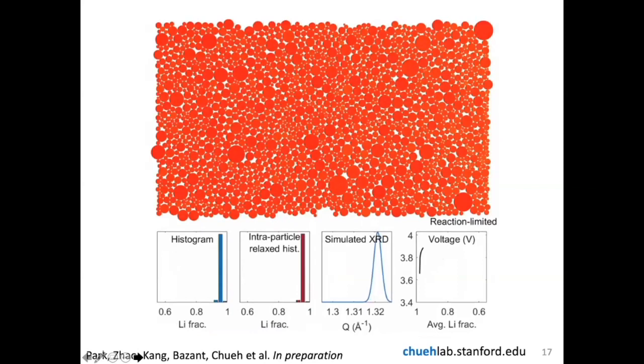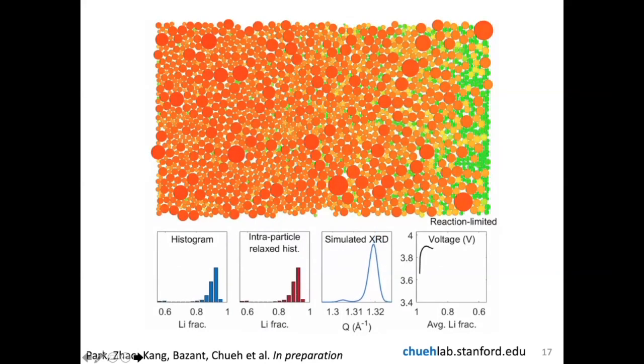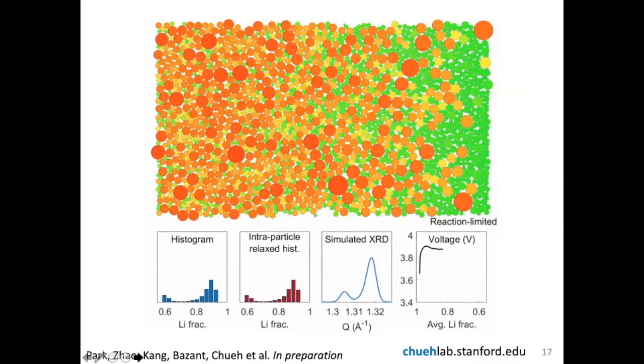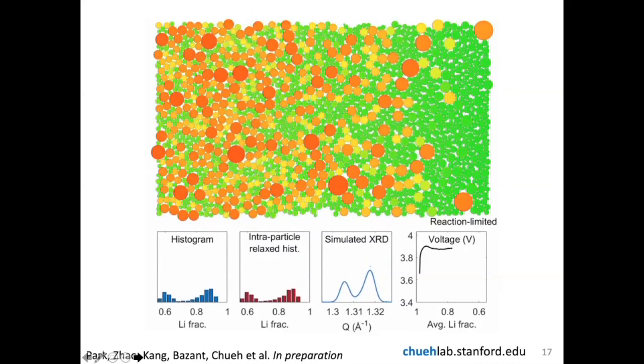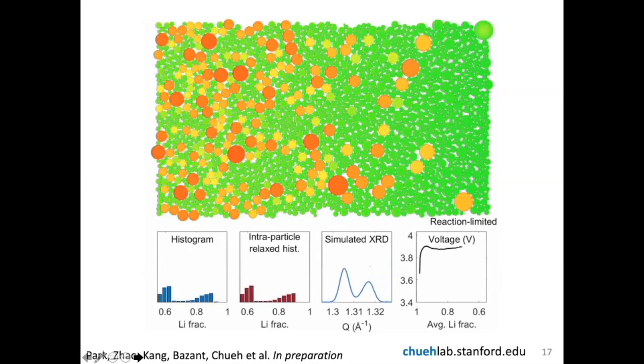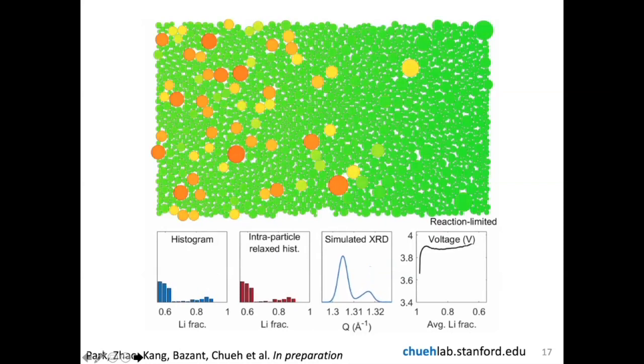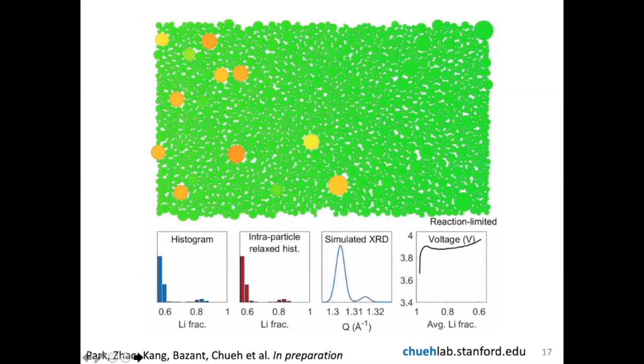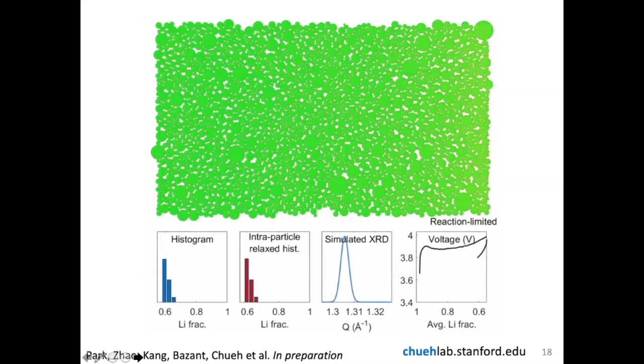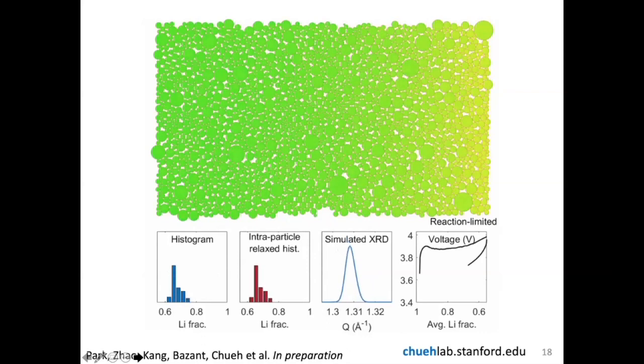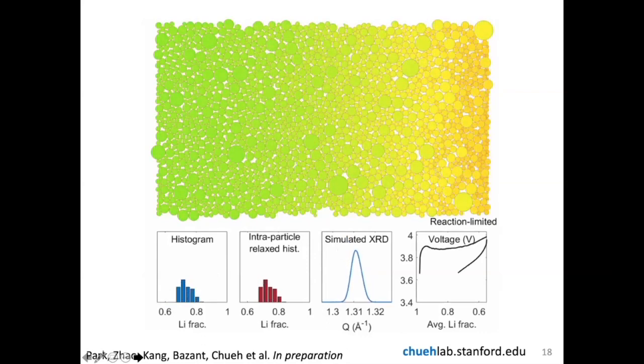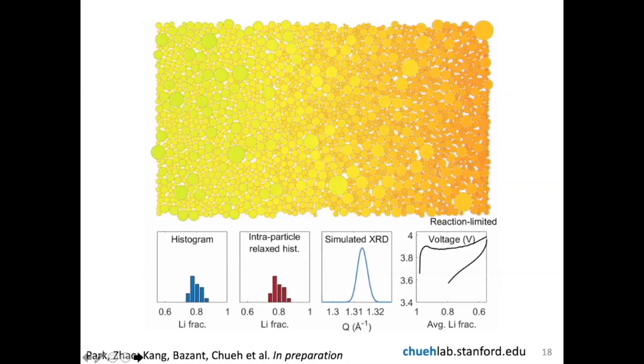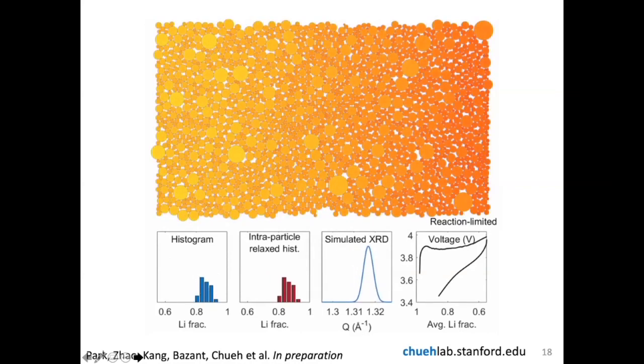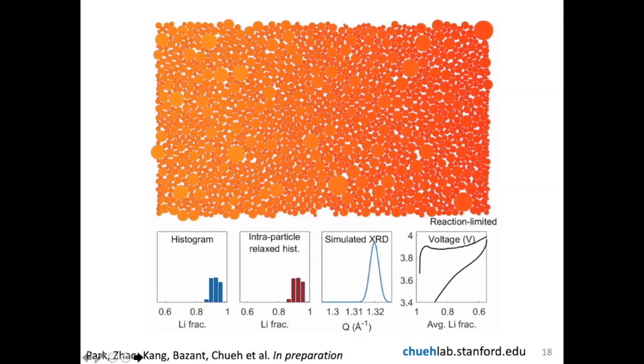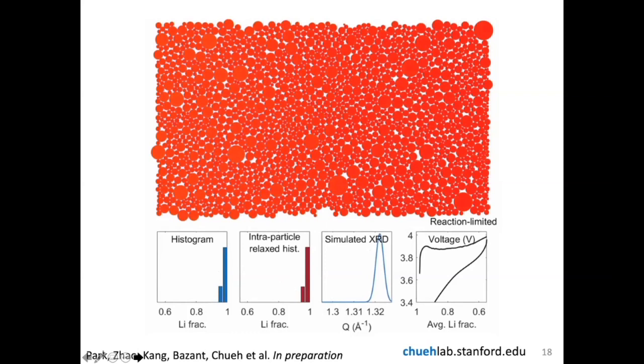This effect actually grows if you have transport limitation in the battery. If you have a very thick electrode, this effect is amplified because, as you have a moving front, the local C rate is increased for a given C rate. And you can see this mosaic behavior occur on charging, but you do not see it on discharging. So hopefully I've given you some insights here on how heterogeneity develops within the material selectively on charging as a result of both interfacial reaction limitation and also how the kinetics depends on the amount of lithium in the system.